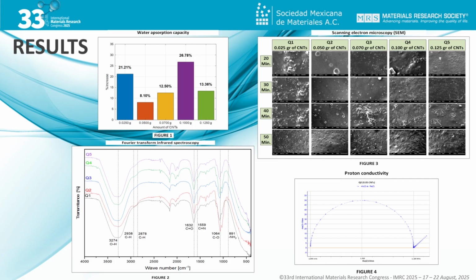The results showed that doping using the glow discharge plasma technique modified the morphology and increased carbon-carbon and carbon-nitrogen double bonds, as well as a single carbon-oxygen bond, which is associated with an increase in the cross-linking level of the membranes, as shown in Figure 2, which significantly influenced the modification of the surface at different exposure times, as shown in the scanning electron microscope images in Figure 3.